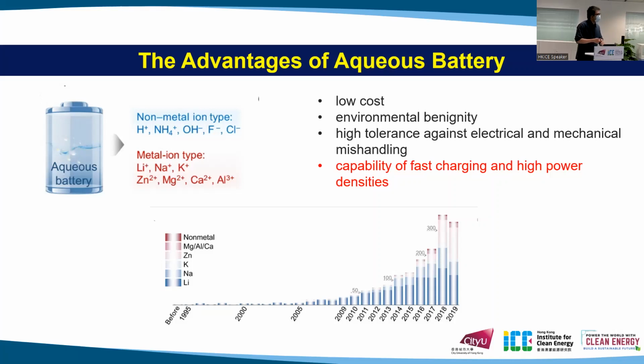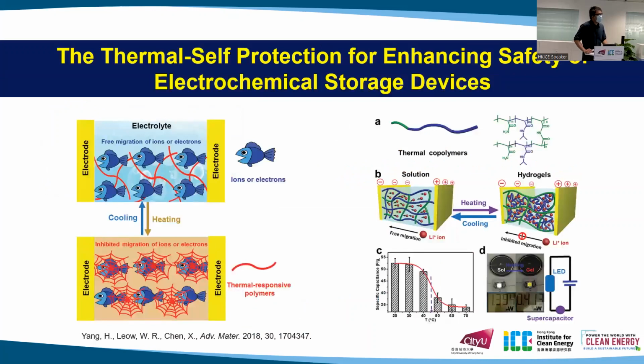And for this one, fast charging is not only an advantage, but also causes some problems. For example, during fast charging, some heat will be generated and accelerate the water splitting and change the pH value of the electrolyte, and as a final result, cause capacity failure. So, in order to solve this issue, instead of adding a thermal sensor in the battery and controlling the battery by the battery management system, people try to put something between the electrodes, so it could work at room temperature, and when it is at high temperature, the battery will stop working. And the most important thing, this process should be reversible.